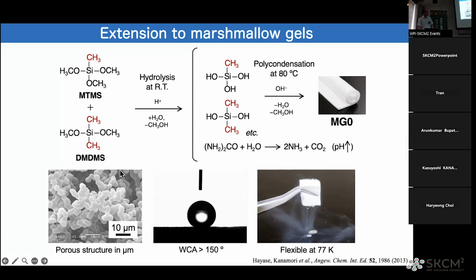And the pore structure is like this, micron size skeletons and pores. So it is easy to absorb liquid inside. And because of the rough surface and the low surface tension, low surface energy of the network, they show very good hydrophobicity. And also they are flexible at very low temperature, like in liquid nitrogen. They still maintain the flexibility, so we can put the marshmallow gel in the liquid nitrogen to soak up the liquid and then squeeze out somewhere else, like in this picture.